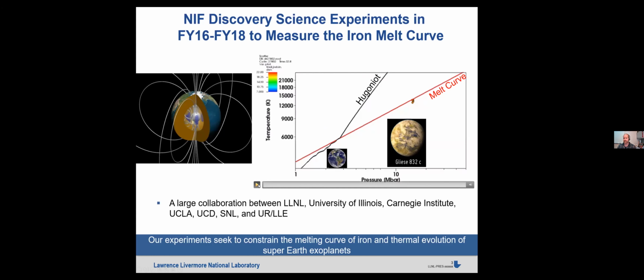So I'll show that one more time. Again, we shock to a state on the Hugoniot, we allow the material to decompress, and then we recompress it relatively slowly to our peak pressure state, where we can then pulse with our X-ray diffraction source to say, is it solid? Or is it liquid? Has it solidified, and to what phase has it solidified? And so we can change the different states on the Hugoniot, mapping out where it solidifies at high pressure.